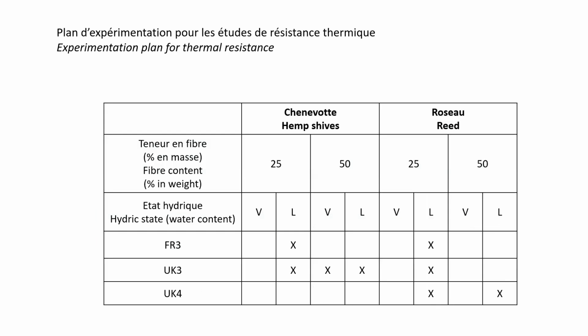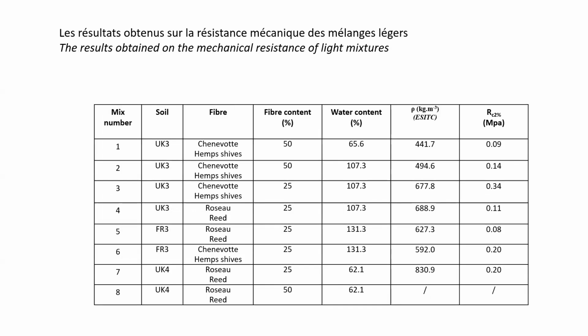We then did the same thing for the thermal mixes, so these light earth mixes. And here we used different fibers. We focused on hemp shiv and reed, and used different proportions. So we tried out 25% or 50% in weight compared to the weight of the dry soil. And we focused on two different hydric states with their water content, either viscous or more liquid, compared to what was planned initially. So in the end, we abandoned this viscous state and just did one test, but it was not very relevant for the light earth mix, scientifically speaking. We studied it, but we didn't use it.